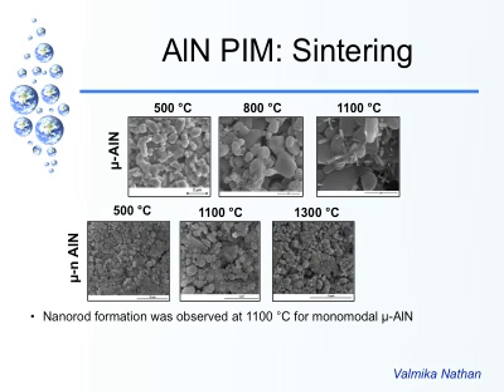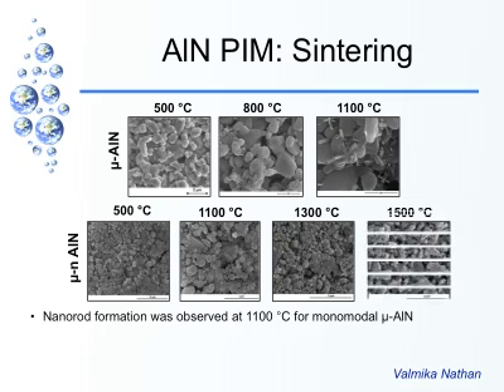Okay. With the micro-nano aluminum nitride, we ended up sintering this material to the point where around 1500 or so it begins to show a good amount of densification. You can see individual particles, and there are some necks, interconnections that are beginning to form, right? And a little bit of grain growth that's occurring. Yes? They're all about 2 microns, roughly. What we think is there's some amount of melting that has already occurred in between, and it's filling up some of the pores. Okay? And there's maybe some dissolution of the aluminum nitride. That's possible. That's a good thing.